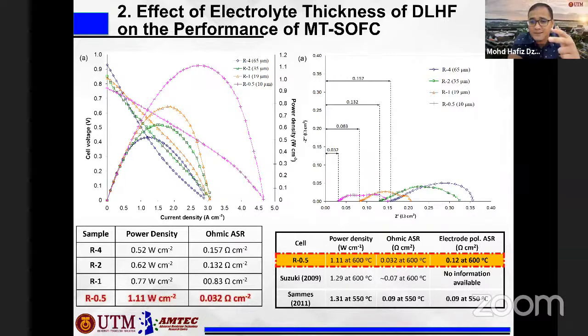Based on the impedance, normally you can measure the ohmic resistance, which comes from the conductivity, either from the electrolyte, the anode, or the cathode. When you see here, the first intercept of your impedance data represents the ohmic resistance. So ohmic resistance comes from the conductivity of the anode, electrolyte, and cathode.